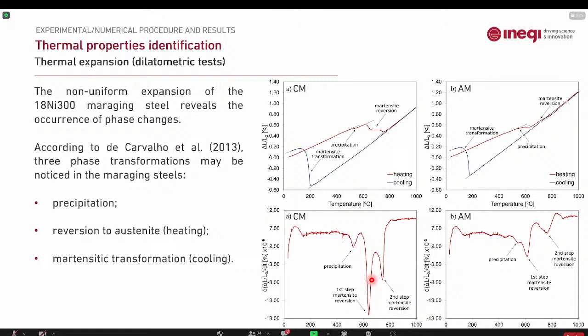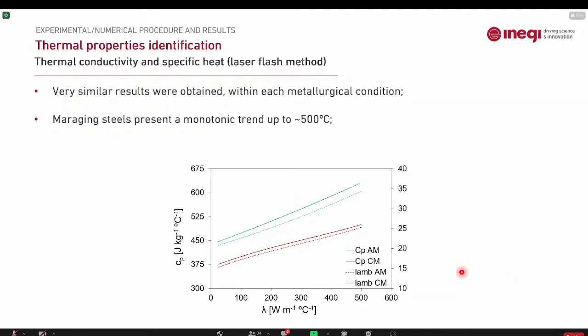For the thermal properties, we measured the thermal expansion coefficient through dilatometric tests, and these tests show that the phase changes occurring in the conventional and additively manufactured are slightly different in intensity, probably showing different austenite content. With regards to other thermal properties, such as thermal conductivity and specific heat, the results seem to be very similar. So there are almost the same values for AM or CM.